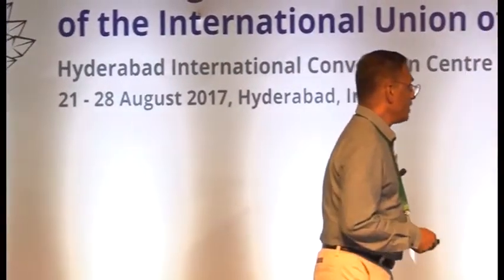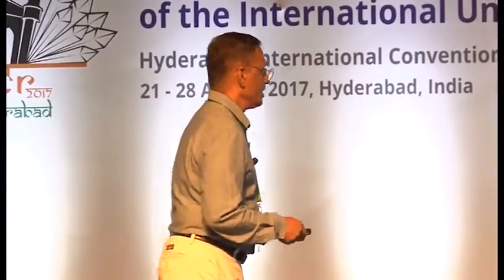Previously, I showed that you can very easily remove the solvents that are present in the lattice or bonded to the metal at very low temperature. In this case, it's the other way. This particular metal complex, as shown here, with lanthanum, praseodymium, and samarium, has got two diethyl ether molecules trapped in it. They're strongly hydrogen bonded.